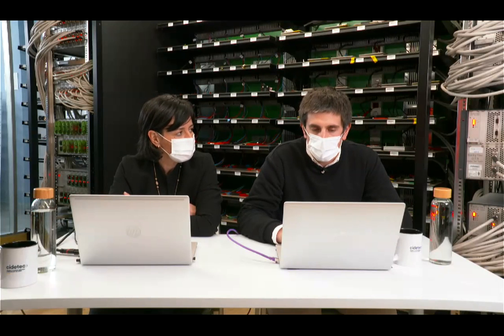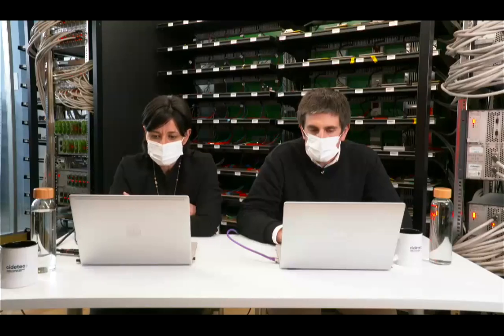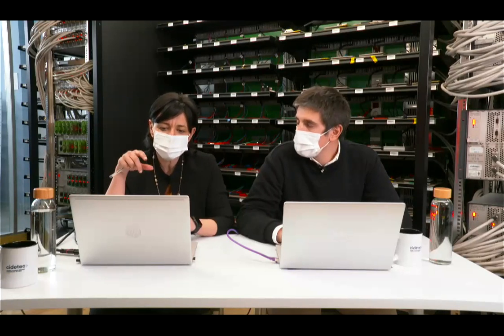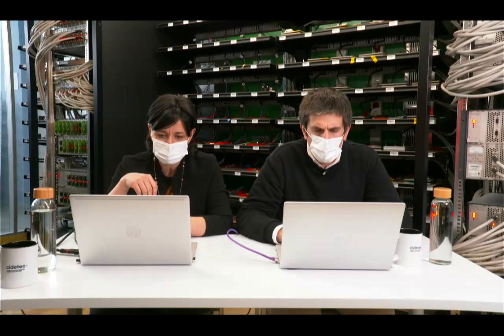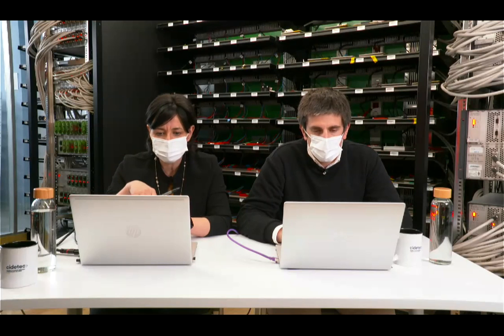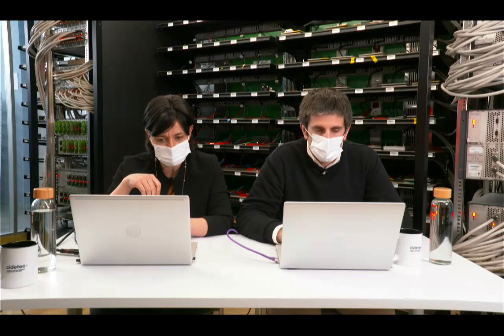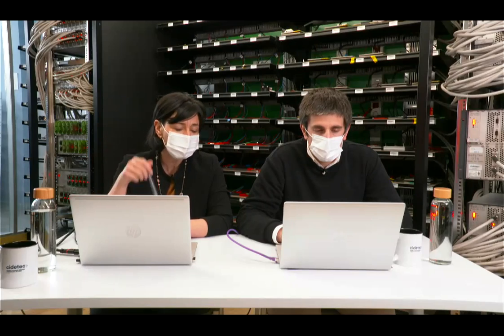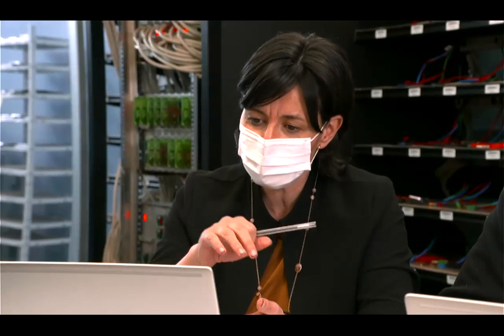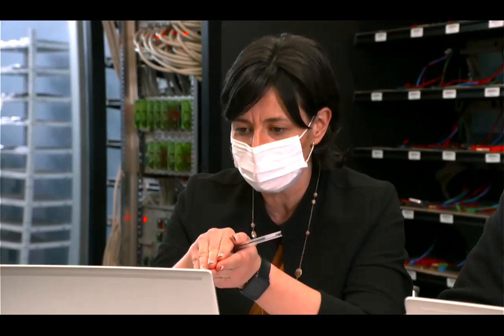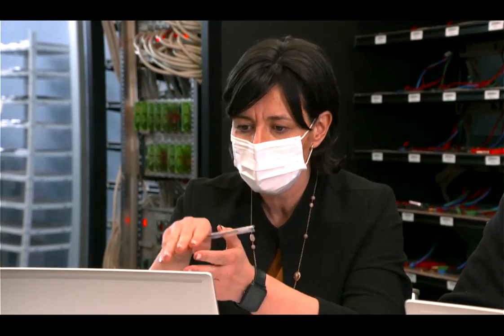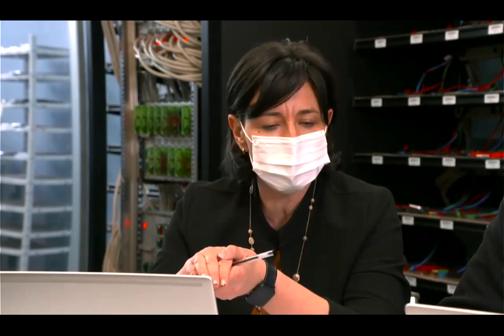We are doing the experiments and seeing how we can achieve this density value, and it's just experimental in the calendaring. Because as we will see later, the electrolyte has to fill all the pores. So we need to keep a balance between the microstructure that we obtained in the drying step and how much we calendar, because we are reducing the volume of the pores in the electrode. So it's important to keep in mind all these aspects.